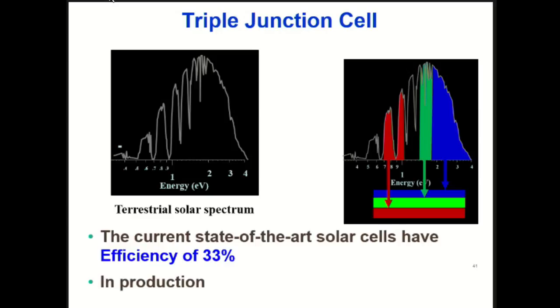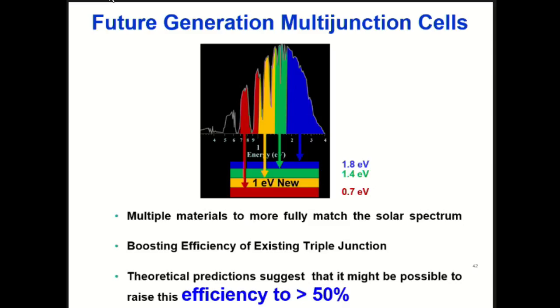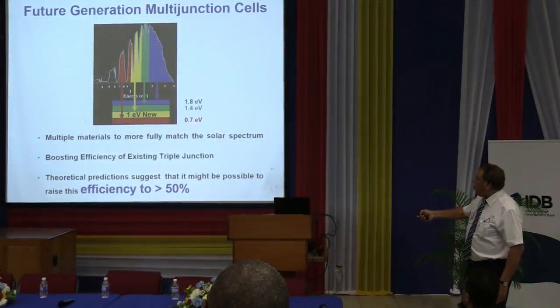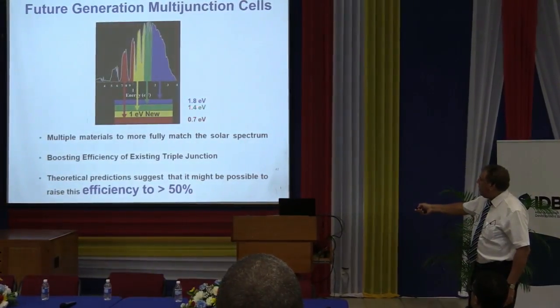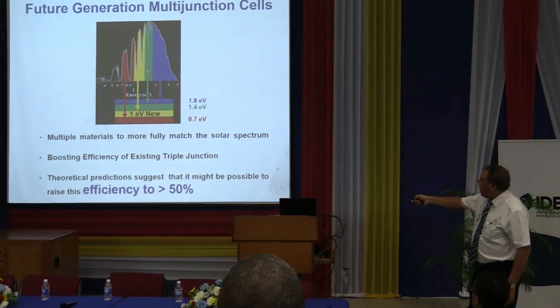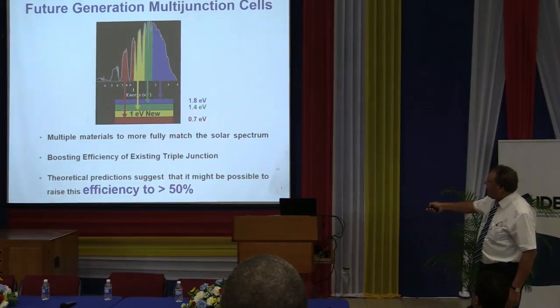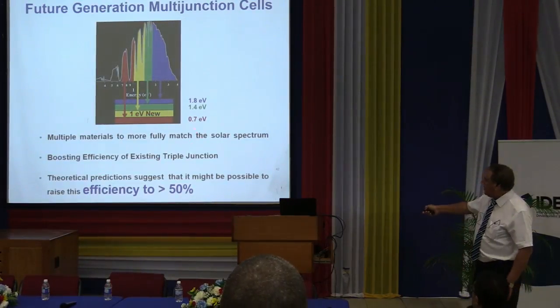So here we've got the state of the art, efficiency about 33%, and they are in production. How am I going to improve it? By adding another junction. The energy I'm absorbing now is for those junctions which are used in space. This energy is about 0.7, 1.4, and 1.8 eV, because all these three materials really match together. So the idea is to find another material system which absorbs 1 electron volt, because you can see there's a big gap between 0.7 and 1.4.